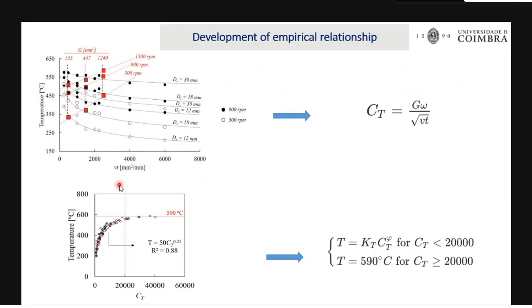Here I use the product of the thickness and the tool travel speed, because these two are involved in heat loss. When you are having slow welding, you will have a different heat loss, and if you are going for faster welding, you will have a different heat loss. So these are the two parameters involving the heat loss, and I'm just using the product of them. Then I plotted the temperature. Here you can see the different shoulder diameters, different tool rotational speeds, and different tool dimensions, that is the geometry parameter.